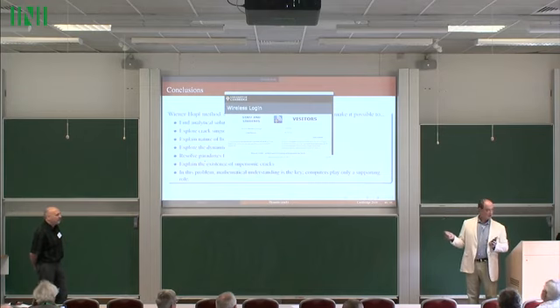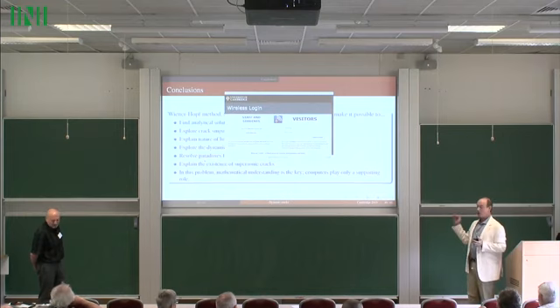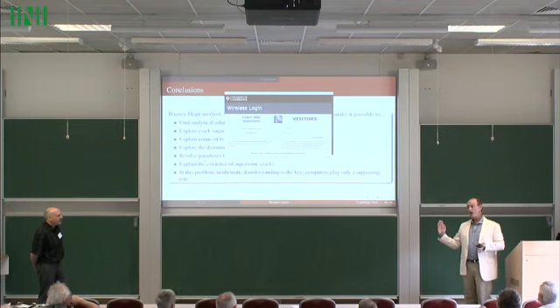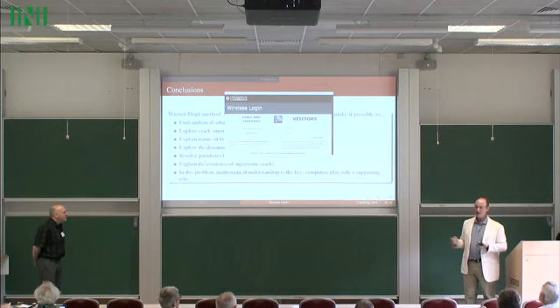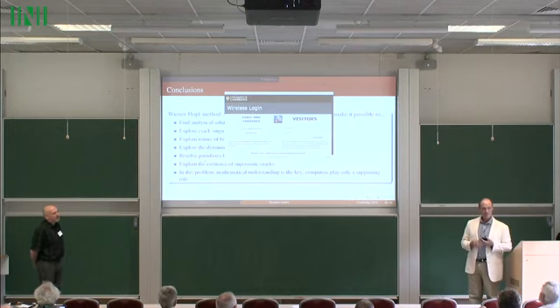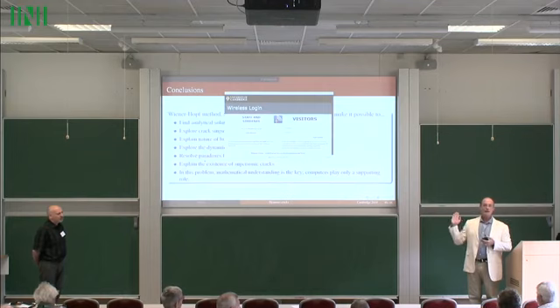I've not seen it. I've had many discussions and some attempts to have such coupled equations without seeing that phenomenon. I think another one, which is the tendency to fracture along planes, you can instantly understand from an atomic point of view. There are natural planes in the solid, so it comes out instantly. I don't see that coming out in any other way either. There is a trace of discreteness in continuum theory, which is a toughness. But this trace plus heat conductivity, still you think it's not enough? Well, yeah, so you can encode atomic information in the toughness.